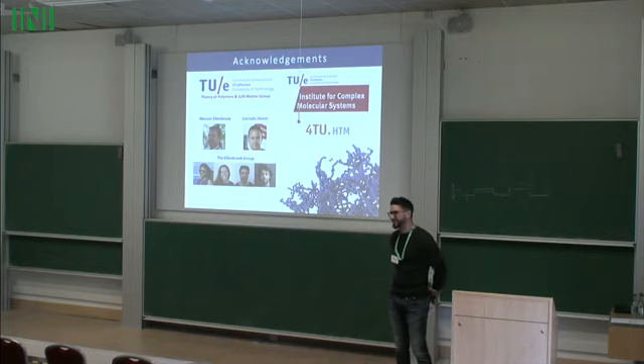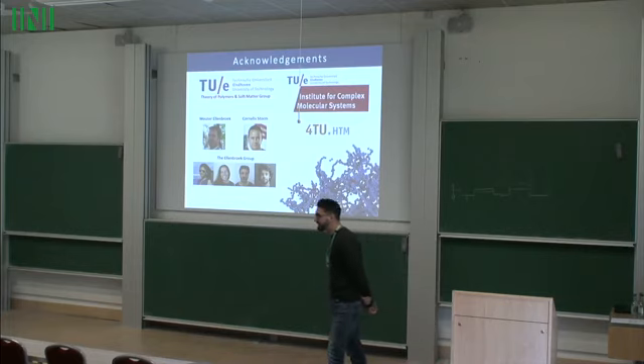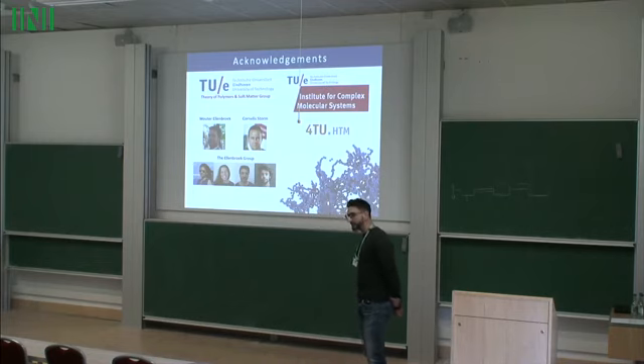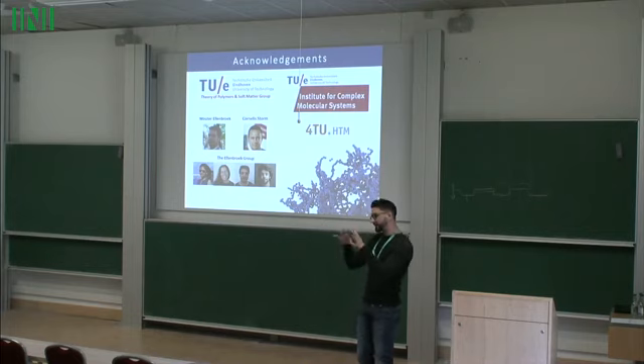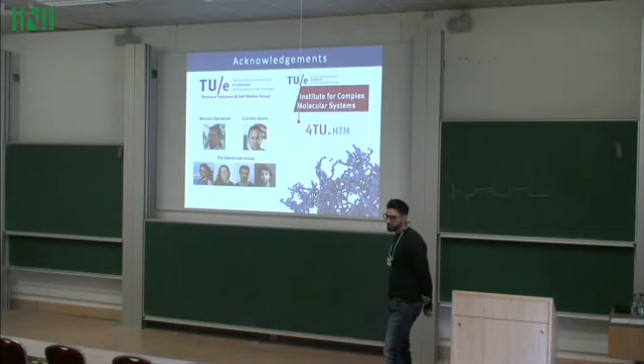Does this have any relation to vitrimers? Vitrimers are similar, yeah. In vitrimers, the bond exchange events are activated thermally. This one's a bit different because with vitrimers, you might imagine star polymers where they have these binding events at their arm tips. So you would have to change the entropy argument a little bit, because here it's really a permanent network that's in place, and you're looking at the entropic bias to form reversible crosslinks by little monomers, basically. So it's a different perspective, but there is some overlap, indeed.